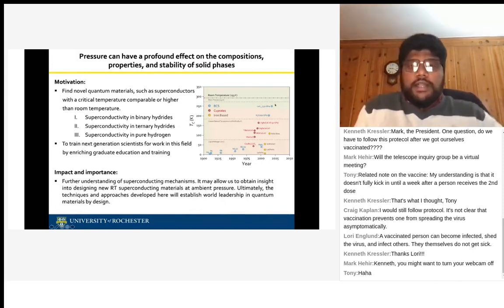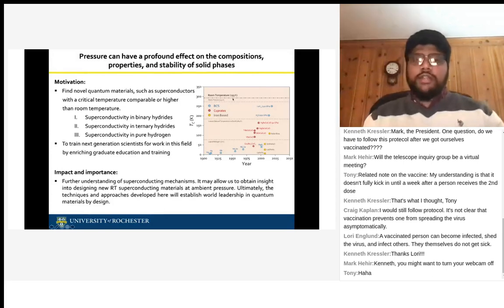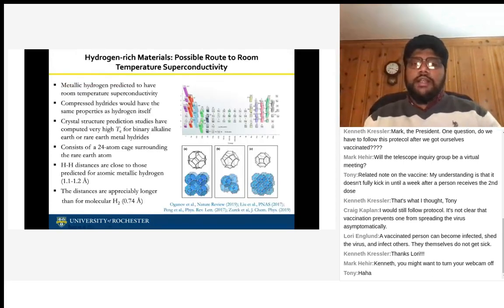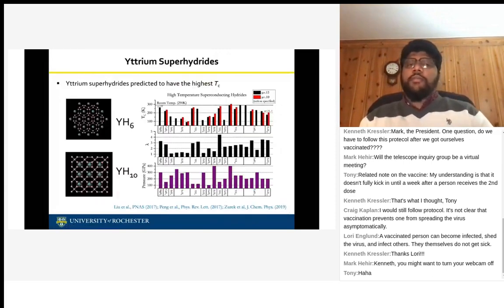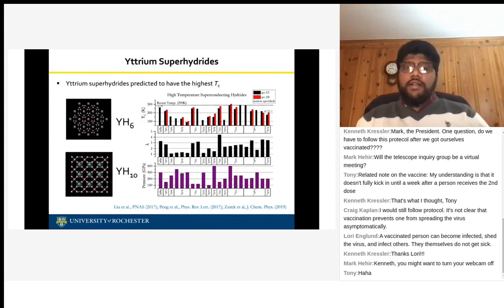This is where we started to think about this research: using hydrogen as a building block to get to these superconducting states. These are the different structures that we use to mimic these similar conditions. One of the interesting materials that we came up with is yttrium hydride. Yttrium can have very different stoichiometries, like YH6, YH10, YH9, and all show superconducting properties. What you're seeing in this graph is the transition temperature for the different chemical compounds. Yttrium here, YH9, YH10, YH6, happen to come close to a room temperature superconductor. So with that, we started studying this material.